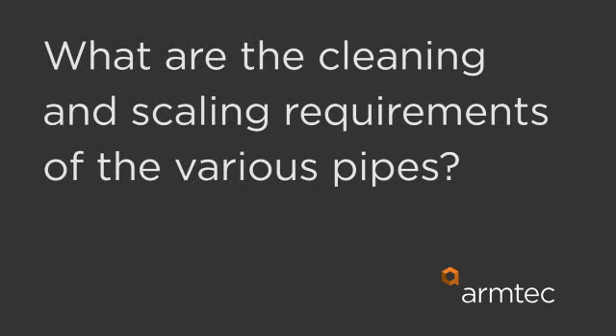What are the cleaning and descaling requirements of various pipes? As far as for a CSP reline or even a concrete reline, basically get as much of the junk and the garbage out of the pipe, of course, and anything loose I would remove from either the pipe or the host structure. We've even relined concrete structures where they've put pieces of plywood to keep the infill from falling in or the grout from going out. But again, yes, you do need to clean the garbage out of the pipe. You need to clean the invert so the pipe is nice and clean.